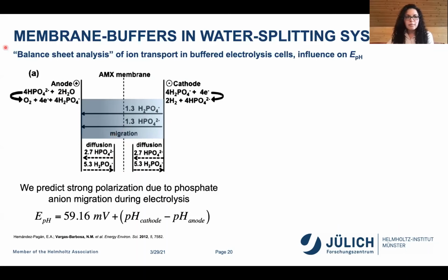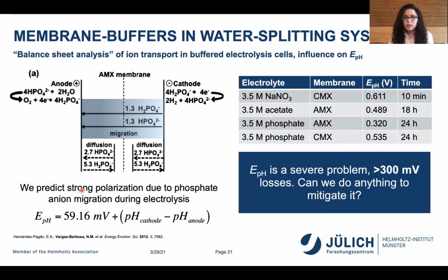And so we did this balance sheet analysis to try and figure out how much of the total charge is being carried via migration versus diffusion, and in which direction everything is moving. In this case, we had an anion exchange membrane. We had the negatively charged phosphate anions constantly migrating from one side to the other while the cell is on, which is already generating a concentration gradient simply by migration. And there's of course diffusion, but is the diffusion actually able to compensate for this fast enough? And the answer to that question is no.